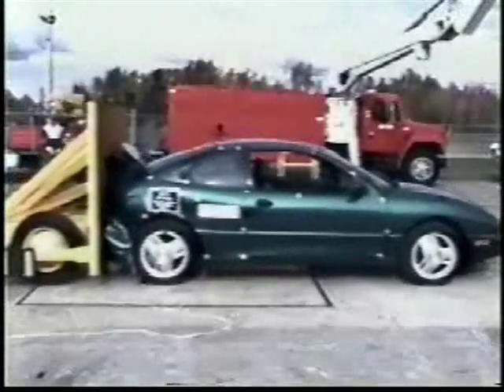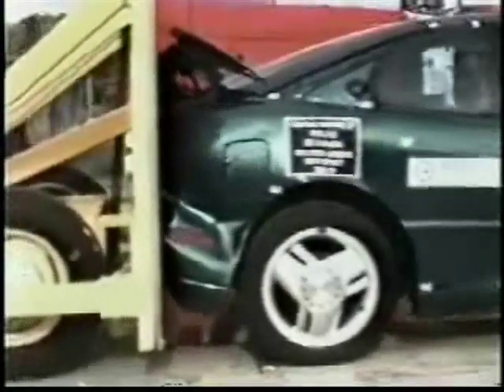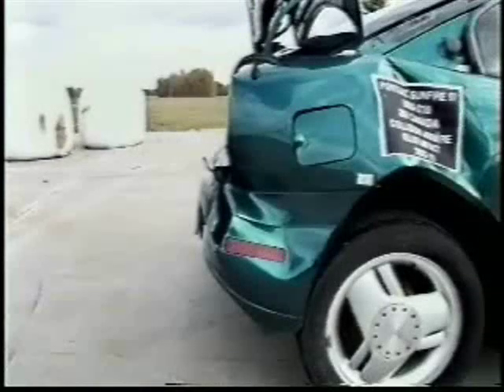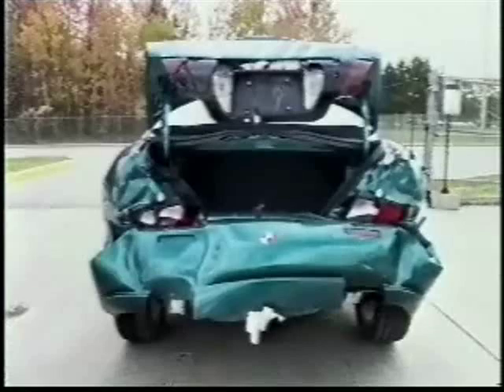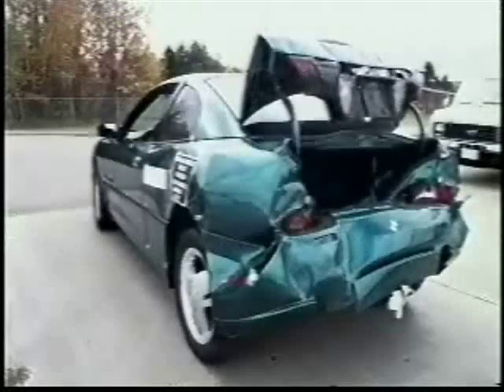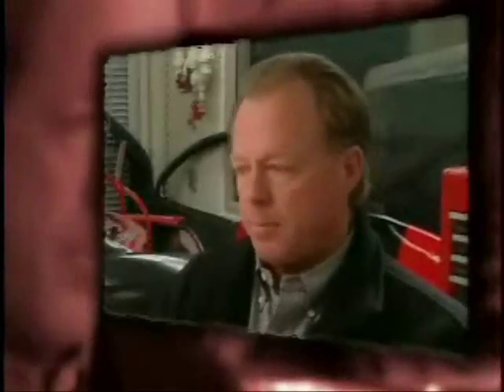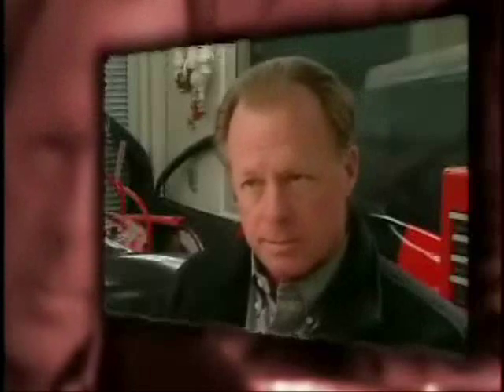In a crash test commissioned by Manitoba Public Insurance, the right rear quarter panel has been replaced using 3M Automix panel bonding adhesive. At an impact speed of 19.3 miles per hour, 3M's adhesive number 8115 separated along similar lines to factory welds. We have had cars come back into our shop after we have panel bonded them in the past and come back in with more damage on it, new damage, and we have noticed that the panels we have bonded on have had the same structural integrity as they have out from the factory. We put a quarter panel on it, it came back, hit again, bent in the quarter panel, but it did not come apart. It did not split the seams.